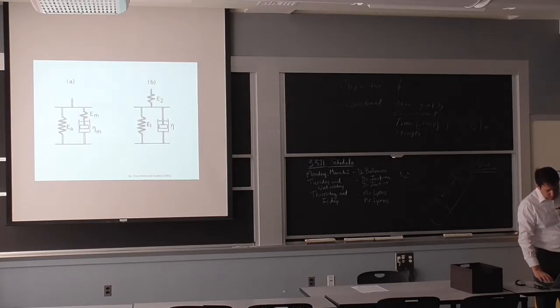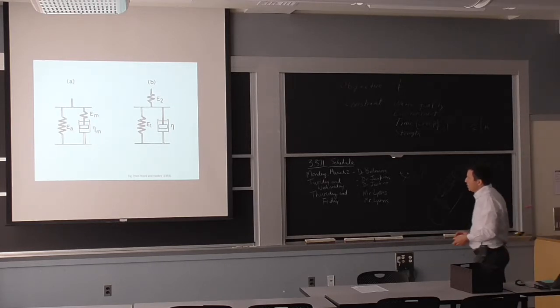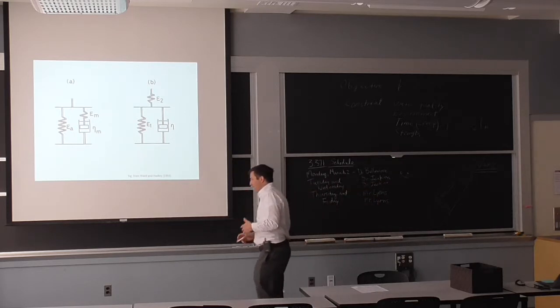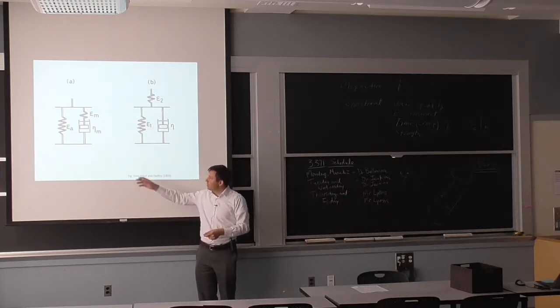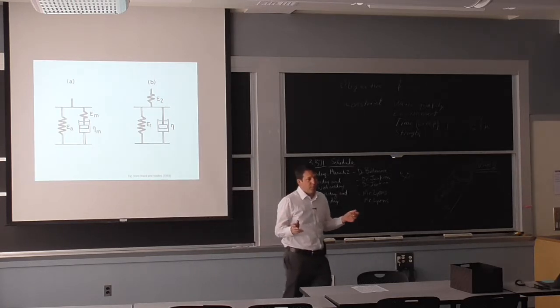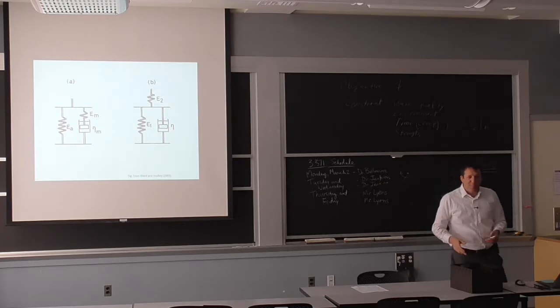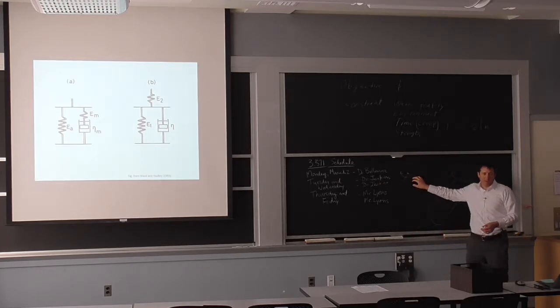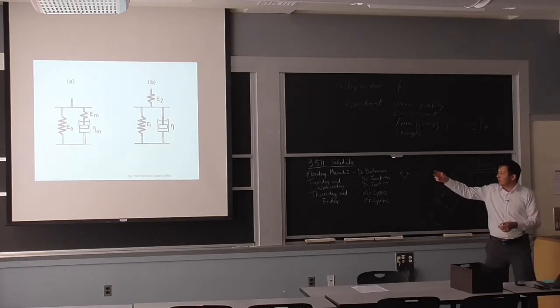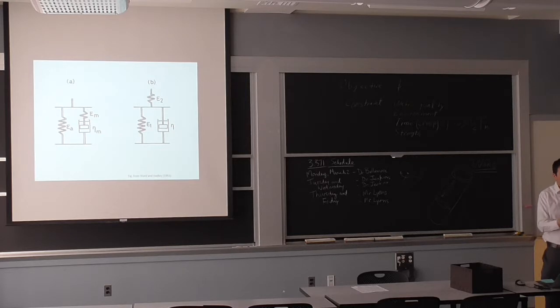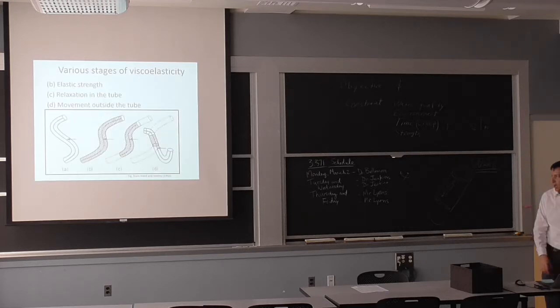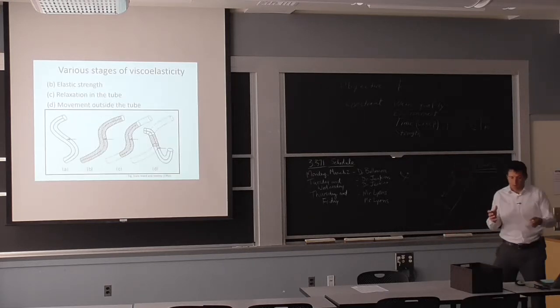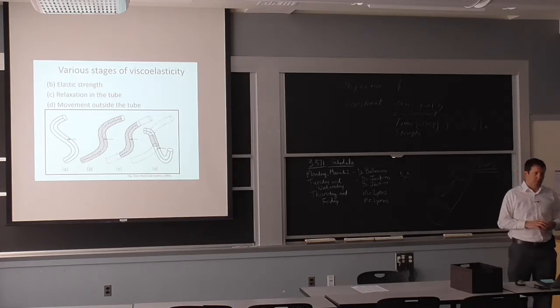So there are a number of models to think in terms of the elasticity and the viscoelasticity behavior of the polymer. It's really good if you're trying to do curve fitting, because these models give you a logarithmic equation for kinetics, which is really what's happening here, because it's thermally activated. So it makes sense that if I take a bunch of springs, in parallel or in series, I can simulate everything. But it doesn't really tie in as much with what's going on from just this simple schematic between the visco part and the flow part that happens on a longer term.